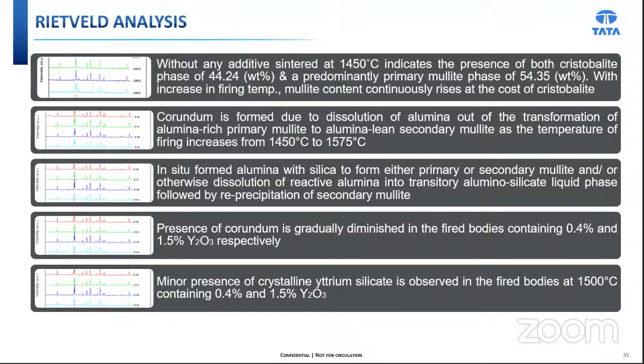Corundum is also formed due to the dissolution of alumina out of the transformation of the alumina, as I have already explained earlier. And alumina secondary mullite forms as the temperature of firing increases from 1450 to 1575. In situ alumina with silica forms either primary or secondary mullite, or otherwise dissolution of reactive alumina into transitory alumina silicate liquid phase followed by reprecipitation of secondary mullite is also observed. The presence of corundum is also gradually diminished in the fired body containing 0.4 to 1.5% yttria respectively. In some cases, with addition of yttria, yttria silicate is also observed.